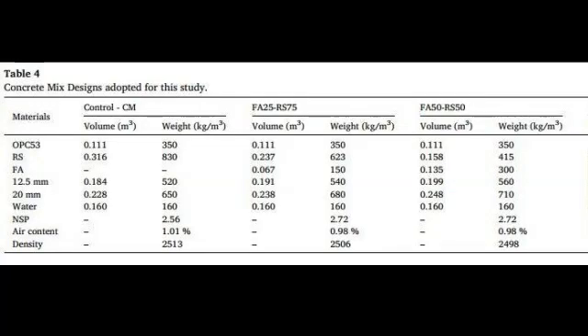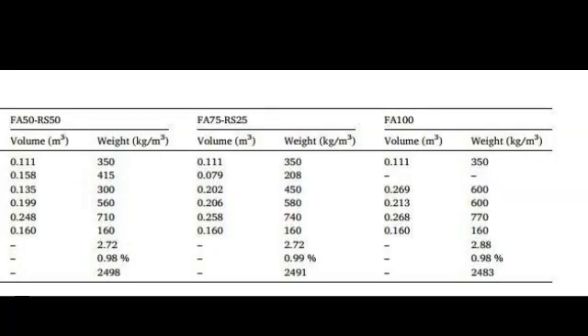And I'm pretty sure I have developed almost 400 to 500 different proportions of admixture and came down to the one which was optimized, which was best suited for concrete containing very high proportions of fly ash. After developing the same, I again carried out the experimentation with paver blocks. I observed a very drastic change in the results. Prior to the addition of this superplasticizer, I wasn't able to attain the strength even after 90 days, as I explained earlier. However, using the same mix design, the same quantity of cement, and by just replacing the conventionally used admixture with the one I developed, I was able to attain the target strength within 3 days, which was very good in terms of the technical performance.